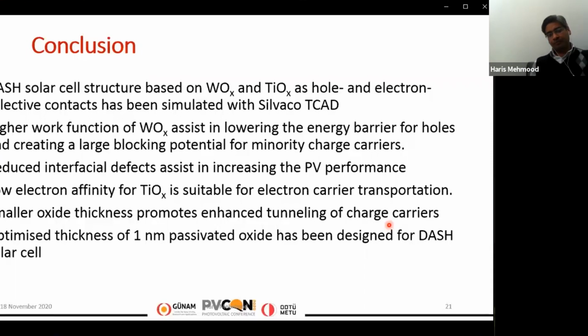Smaller oxide thickness promotes the enhanced tunneling of the charge carriers, and the optimized thickness of 1 nanometer has been simulated to be taken as an optimized thickness for this proposed device solar cell.